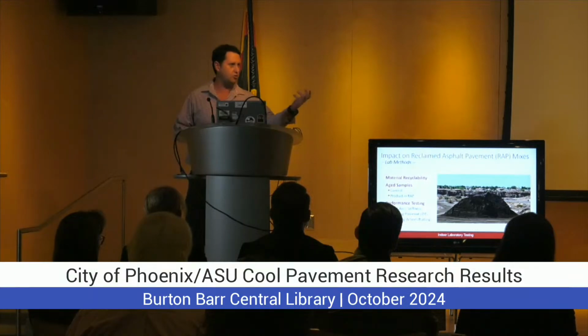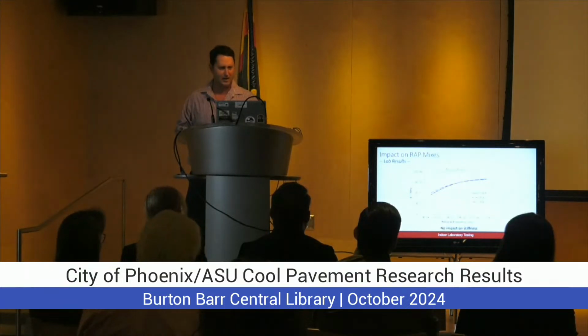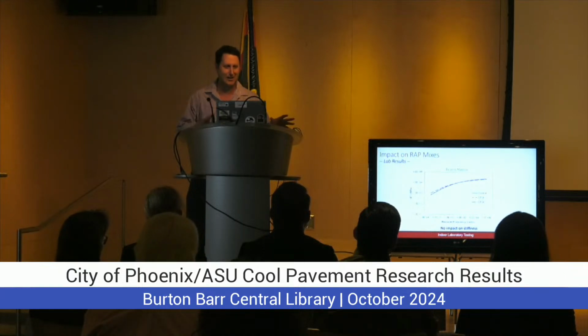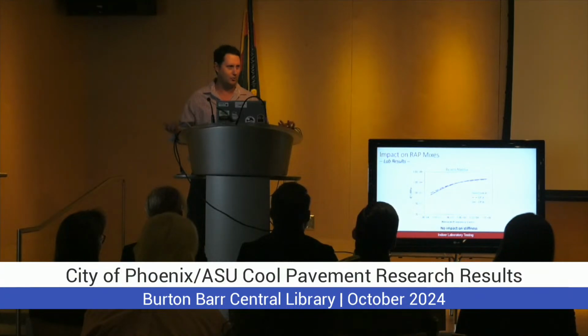And we compared a conventional RAP mix with another RAP mix that included these other products. I don't expect you to understand this graph, but the bottom line is that all these curves overlap each other, meaning that there is no difference. So in the future, if we want to apply this coating, mill the asphalt, and use those millings as RAP for new mixes, it will not have any problems in terms of the stiffness of the material.